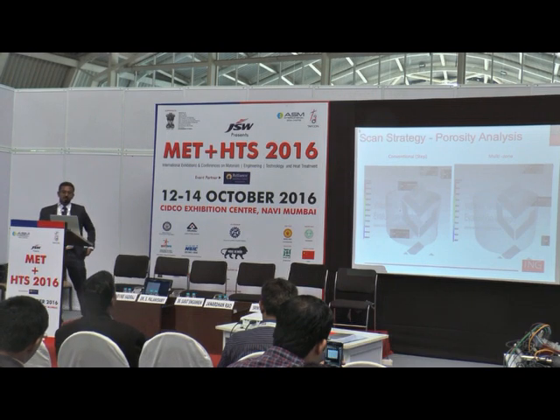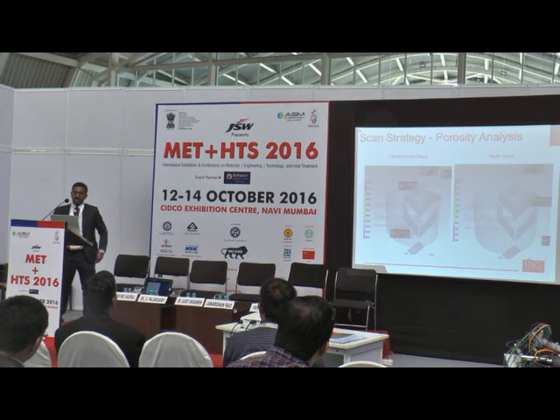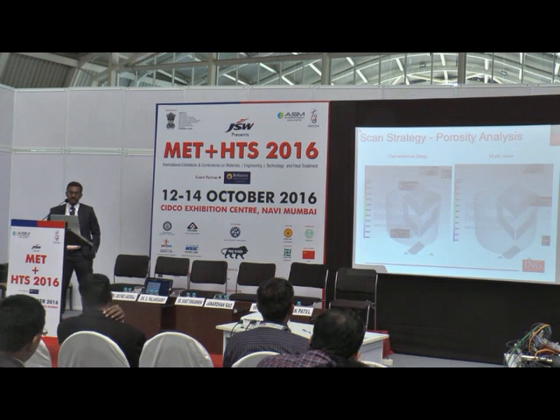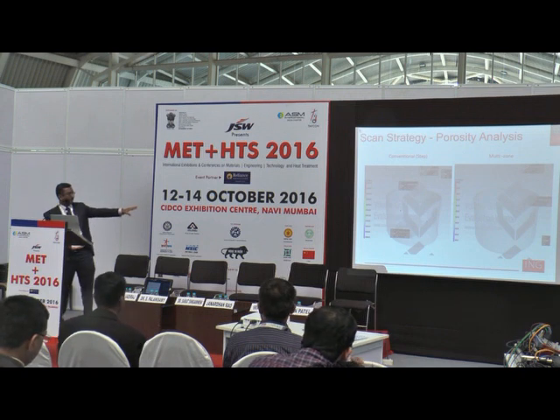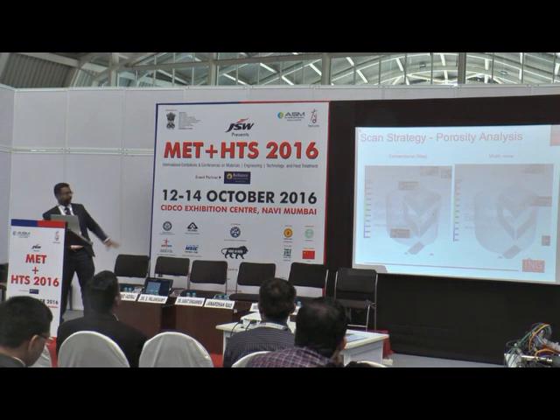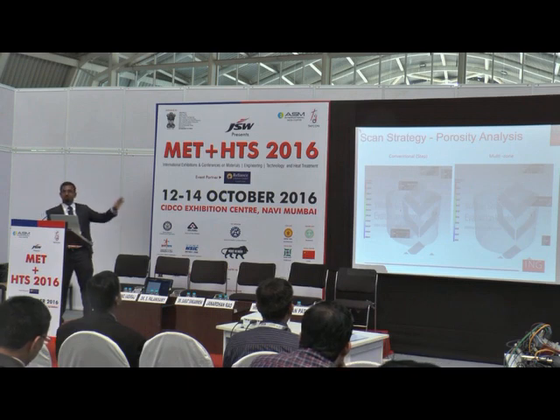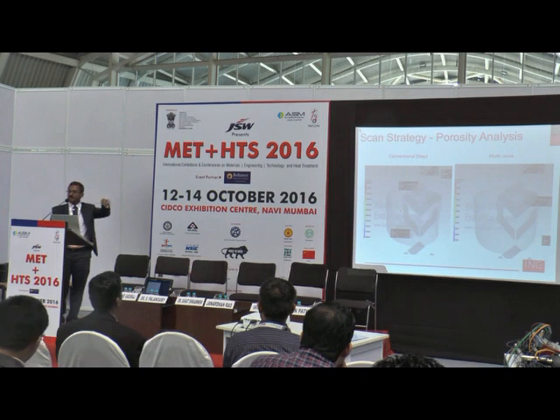The conventional strategy compared with the multi-zone strategy which we have used. Again, I'm not sure you can visualize here. There's a porosity in the CT scan image here. Compared to the multi-zone, we didn't get any porosity. So scan strategy also plays an important role. How do you scan the laser when you melt the powder particle?